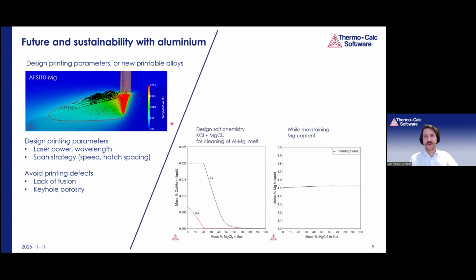Moving on a bit towards recycling now, salt fluxes are used commonly to clean the aluminum melt, and we have descriptions in our databases that can help model this. So we can design the salt chemistry for the optimal cleaning of the aluminum melt. Here we have a potassium chloride mixed with magnesium chloride, and we're increasing the proportion of magnesium chloride in the salt flux to look at removing sodium and calcium impurities from the melt. So we can see we will reach a satisfactory value here, while also maintaining the magnesium content in the melt.